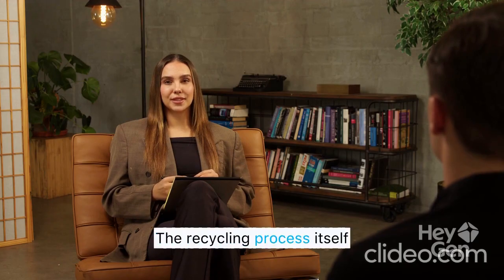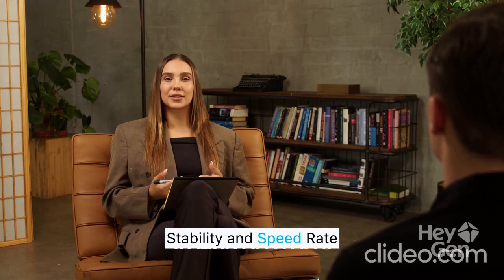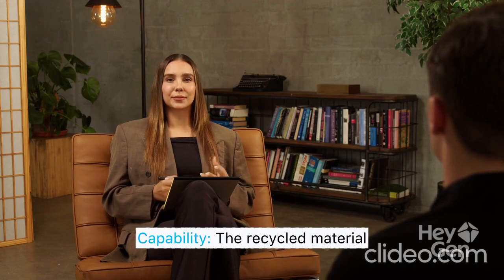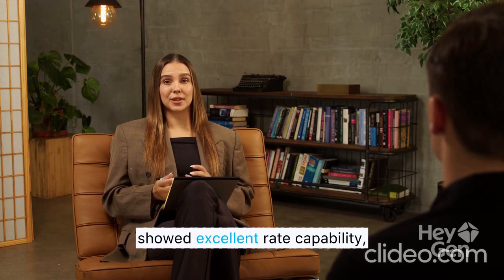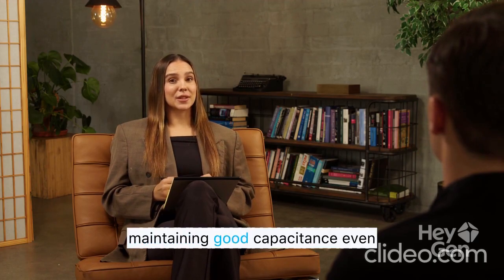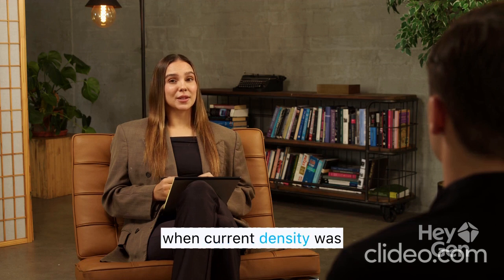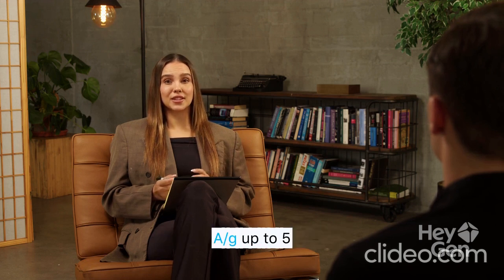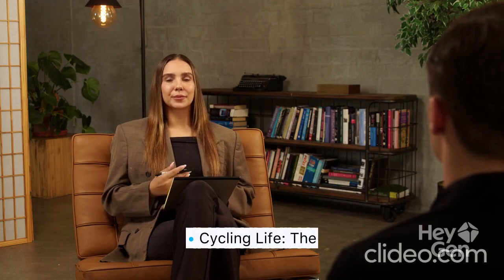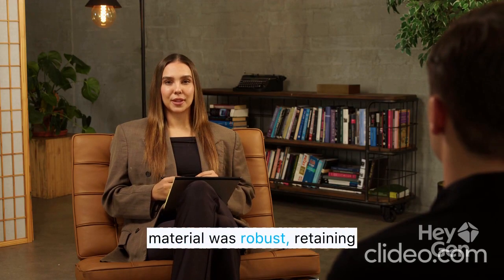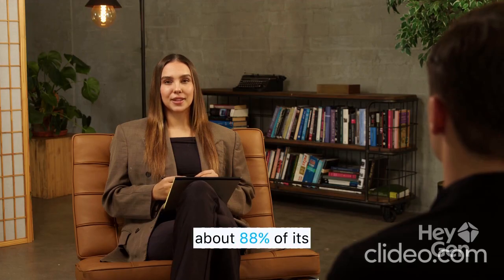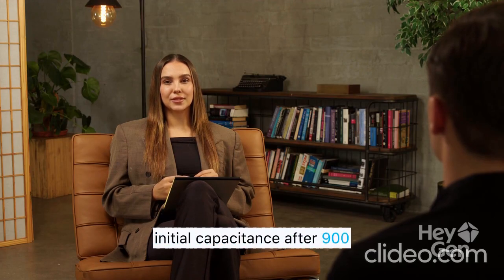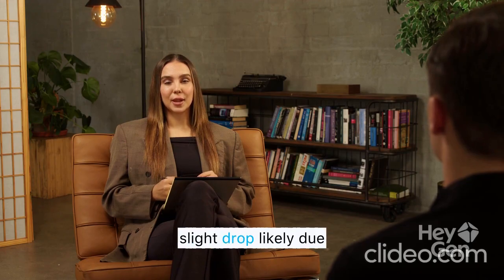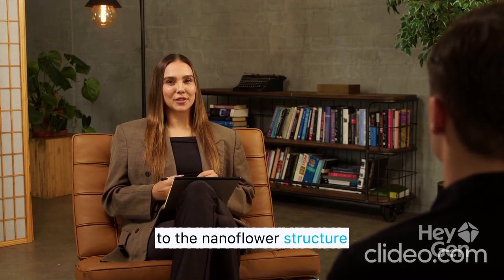The recycling process itself drove the superior result: stability and rate capability. The recycled material showed excellent rate capability, maintaining good capacitance even when current density was drastically increased from 1 A/g up to 5 A/g. Cycling life. The material was robust, retaining about 88% of its initial capacitance after 900 cycles, with the initial slight drop likely due to the nanoflower structure settling in.